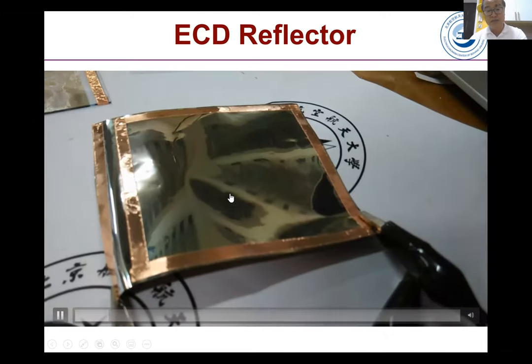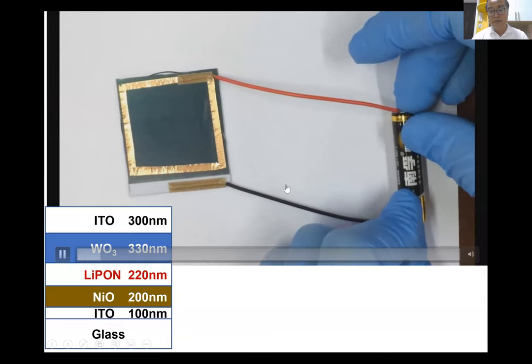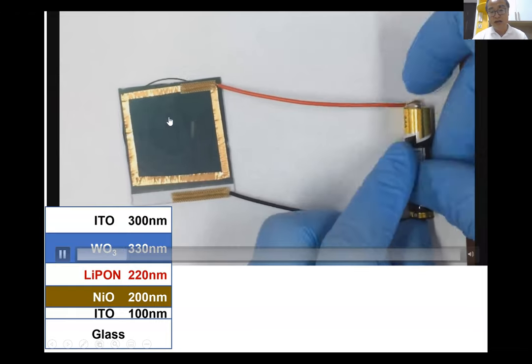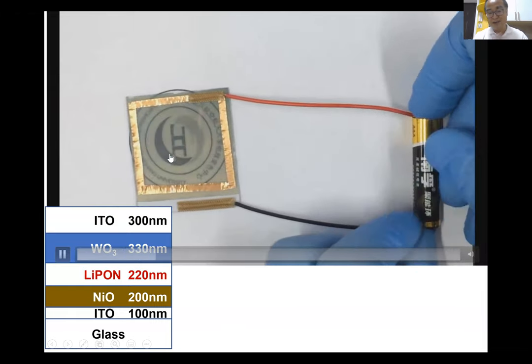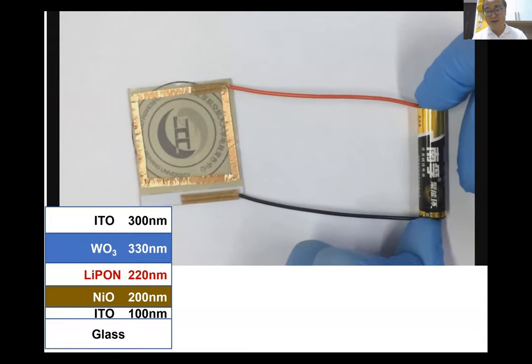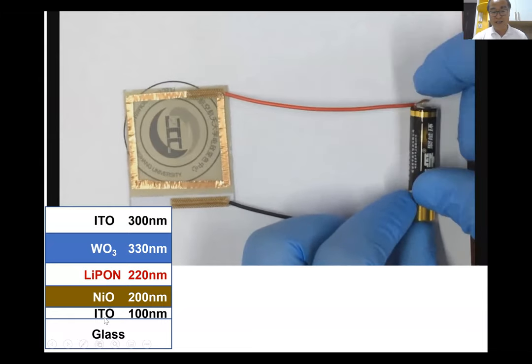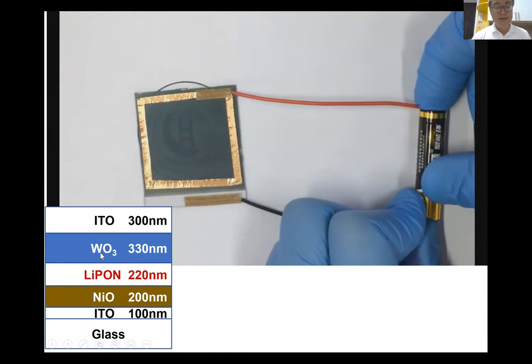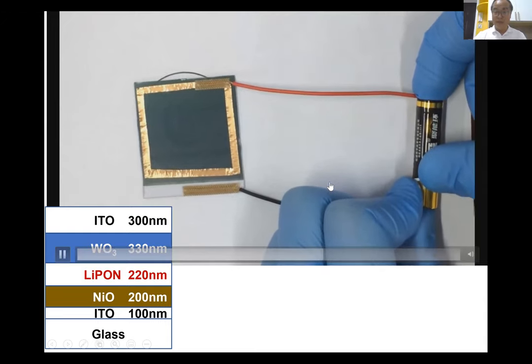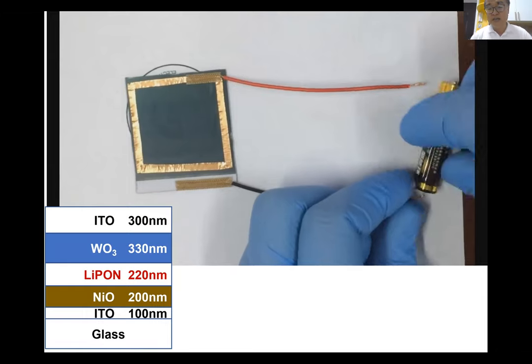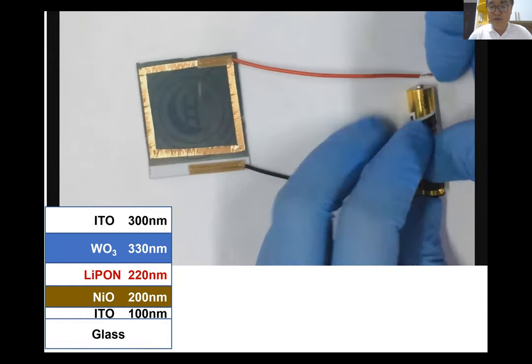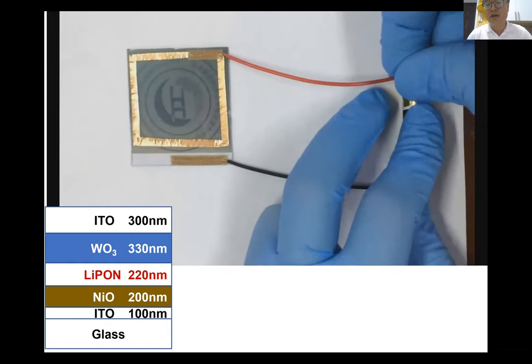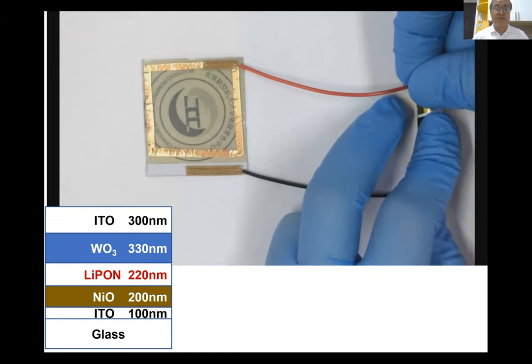And this is a small device made by my students in the laboratory, using small glass and a battery to drive such color changing between transparent and not transparent. You see, the structure is glass, ITO layer, nickel oxide layer, and LiPON layer. And this is the electrolyte layer, tungsten oxide layer, ITO again. Something very simple, but the coating technologies are vacuum coating technologies, which we have been developing by ourselves. We are developing not only the coating technology, but also the equipment ourselves. Okay, so this is also for the infrared, far infrared.